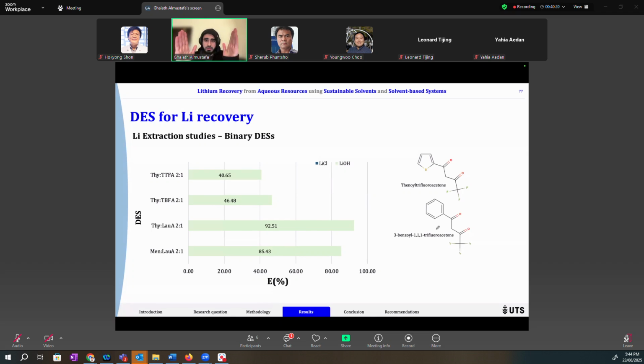We looked at the extraction efficiency at two different feed streams. We wanted to understand the effect of pH. So we used lithium chloride and lithium hydroxide, where lithium chloride is basically pH neutral, around 7, and lithium hydroxide has a pH of around 12.2. And as expected, we did not find any extraction for all 4 DESs from the lithium chloride solution. However, we found significant extraction for the lithium hydroxide solution.